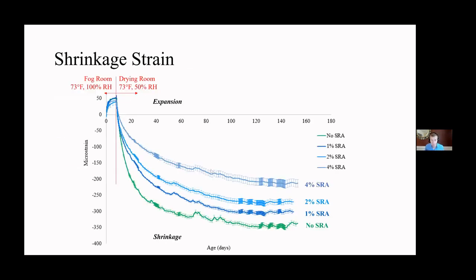Now, I'm showing on this graph, on the y-axis is strain, how much it moves, and on the x-axis is time. As you're curing your concrete, concrete is like a hard sponge. That's what's going on. So as you cure and add water to it, look at that. It grows, it expands. And then once you put it in a drying room, this is 73 Fahrenheit, 50% relative humidity, the sponge shrinks. And the one with no SRA shrinks the most. Then here's 1%, 2%, and 4%.